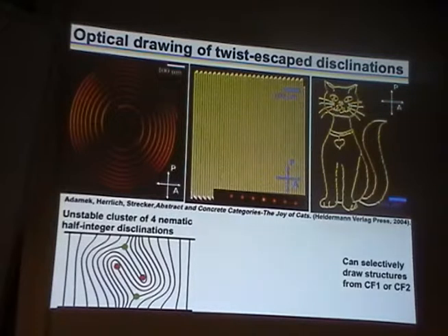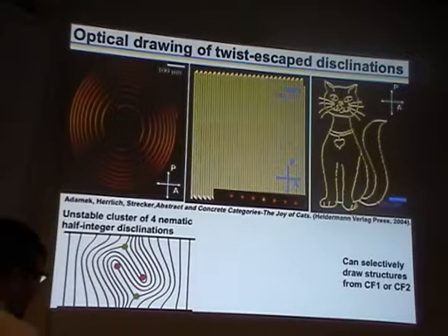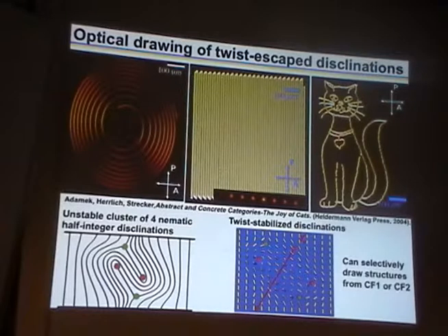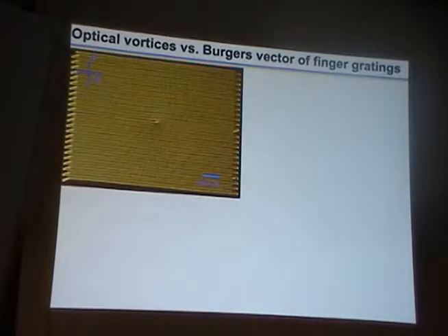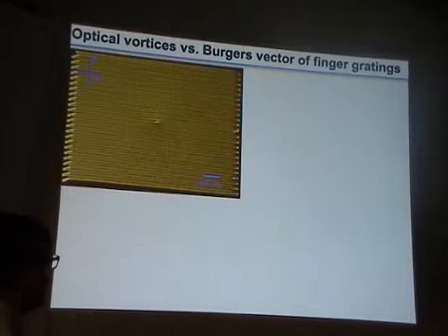And the whole reason we can do all of this is because the defects, which are non-singular lambda disclinations in all of those cases, allow us to locally introduce cholesteric twist in a system which would like to form twisted structures, but is prevented from doing this due to confinement and boundary conditions, right? So introducing twist with helical axis in here being tilted allows to locally minimize energy and form those long-term stable structures.